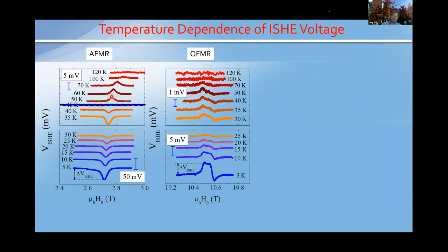So now if we look at the data above 45 Kelvin, these two signs actually agree. This quasi-ferromagnetic resonance peak sign agrees with this antiferromagnetic resonance peak, which both should have the same handedness, okay? So what happened at low temperature? From the experimental point of view, we see the sign reversal. So we know that it's the spin current.